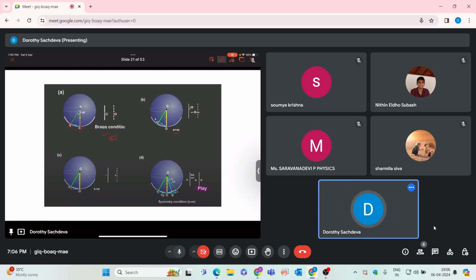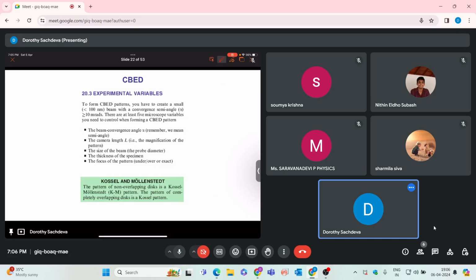Also, when S is zero, you can have this symmetry condition. Then you can have your positive G as well as the negative G. So this will give you the Kikuchi lines and then you can find the diffraction pattern in this case. Then we have already discussed the convergent beam electron diffraction in the previous classes. So here basically TEM works in the parallel beam mode.